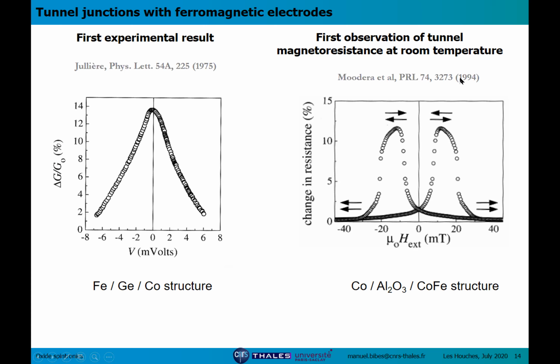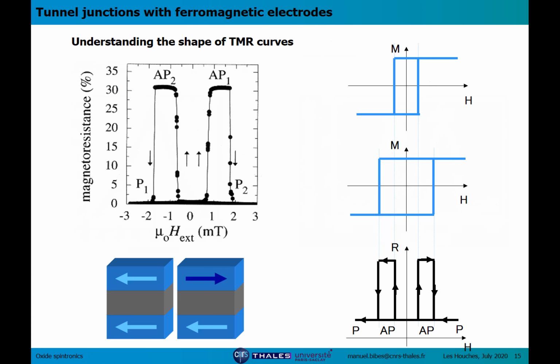The first conclusive results came about 20 years later in two groups: the group of Miyazaki in Japan and the group of Jagadeesh Moodera at MIT, the same group as Meservey and Tedrow. This was with junctions using aluminum oxide as a barrier, which is a very good insulator. And you can see what we call a TMR curve. We have a strong variation of the resistance as you sweep the magnetic field. The resistance is low at high magnetic field, and then as you decrease and reach negative values, you get a strong increase and then a decrease, and the curve is basically symmetric as you go back to positive magnetic field. So how can we understand the shape of these TMR curves?